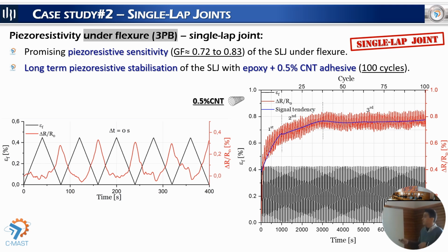We also perform long-term tests, also flexural tests, to see the stabilization of the signal over time. Here we perform 100 cycles, and we observe that after 25-30 cycles, the signal tends to stabilize in a plateau value and with a regular amplitude, which is also important to make some conclusions about these variations.